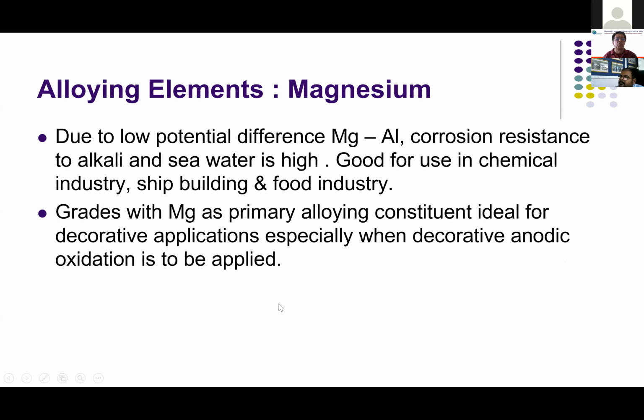Again, back to alloying. Due to low potential difference between Mg and Al, corrosion resistance to alkali and seawater is very high. Therefore, use of magnesium in chemical industry, shipbuilding, and food industry is recommended. Magnesium bearing alloys. Grades of magnesium as primary alloying constituent is ideal for decorative applications. You see, there are some alloys where the magnesium is about 5-6%. These are mainly used for decorative parts where you can get very good colors and very good surface finish.